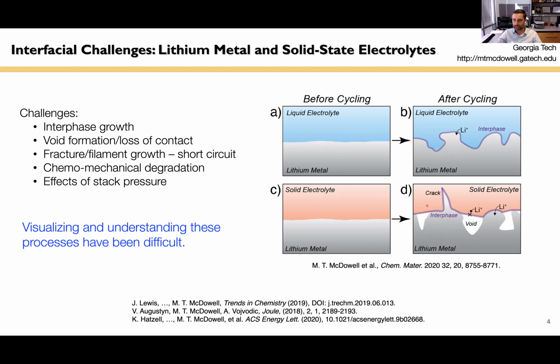If we look now at the solid, it's a little bit different. We have a nice clean interface to start with between lithium metal and the solid electrolyte. But after we cycle, lithium metal has changed its shape. There are now some areas where there's a void and there's loss of contact. And lithium metal can also grow through and fracture the solid electrolyte to cause short circuits. So this illustrates that a solid-solid interface is fundamentally different from a solid-liquid interface, and there are different sorts of challenges associated with it. Historically, and even in recent times, visualizing and understanding these various processes has been difficult. So that's one of the things that my lab focuses on.